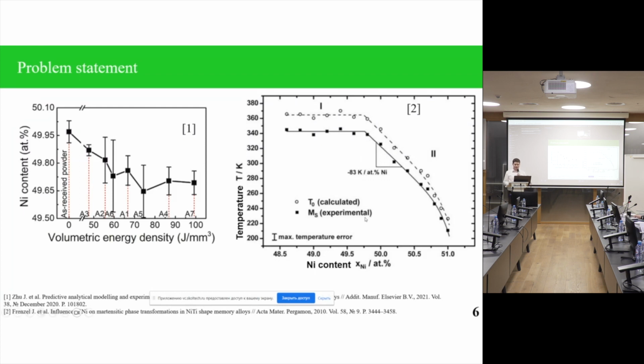And this tells us that by changing the chemical composition of the alloy by 1%, we have a shift in transformation temperatures of 80 degrees, which is quite a lot for any application that I mentioned. So for example, if we want to 3D print a stent for a coronary vessel, we need to have a transformation temperature just below the temperature of the human body by a degree C. So we want to have the exact transformation temperature. But for now, we can only measure this transformation temperature after the manufacturing.